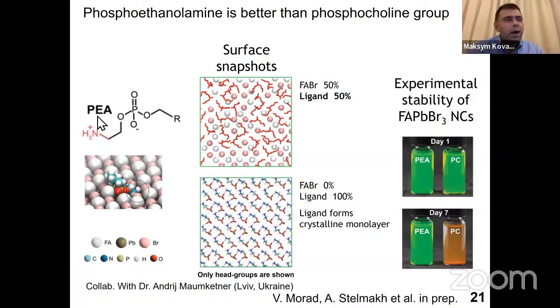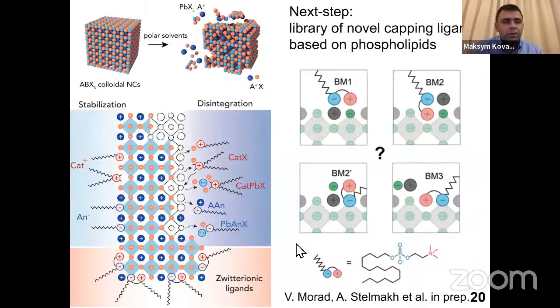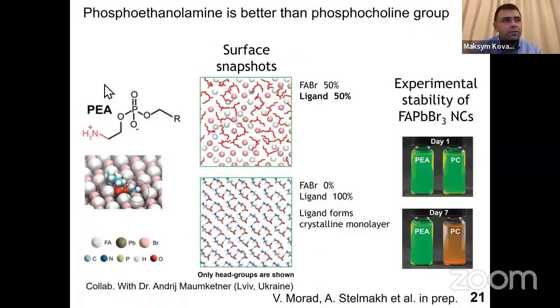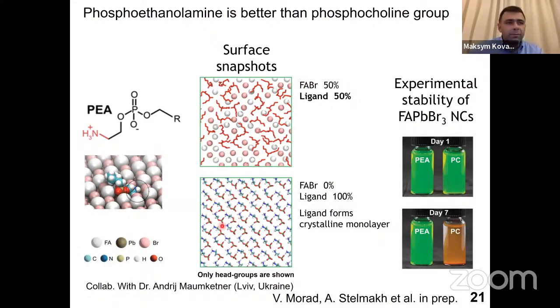And when you take this version, the one which is primary ammonium, so we call it PEA, this group is phosphoethanolamine. And just for the sake of language, this is phosphocholine, and this is phosphoethanolamine. We find that this ligand, because the size of this group is quite a bit smaller than the trimethylammonium group, binds much better to the pocket which is initially occupied by cesium, and so basically it binds much better to the surface, such that you can actually have full monolayer coverage of the surface with a phospholipid of this kind.